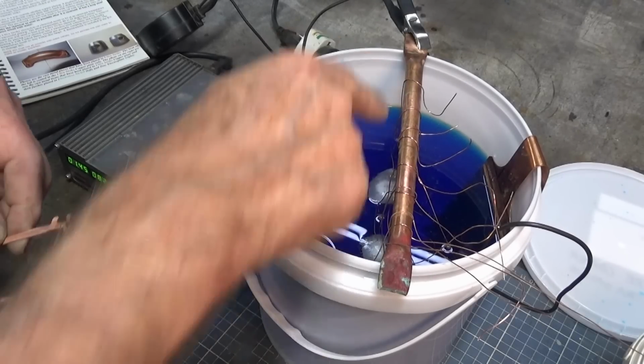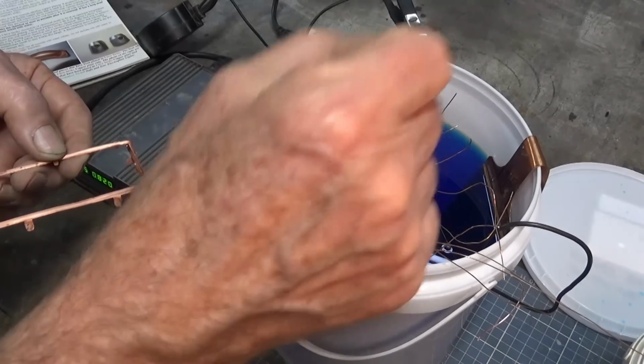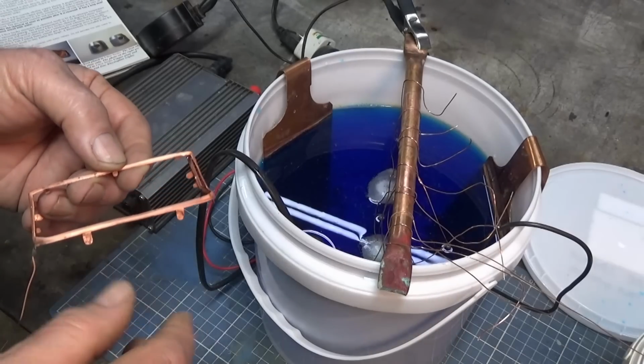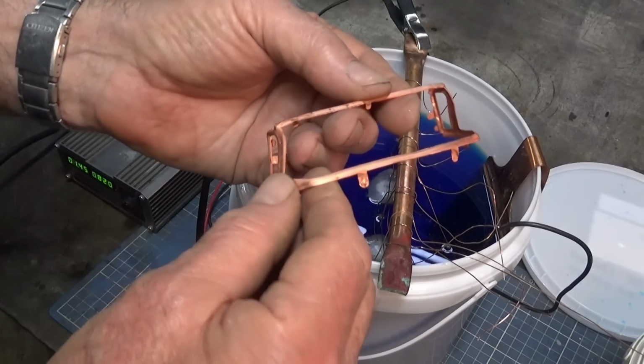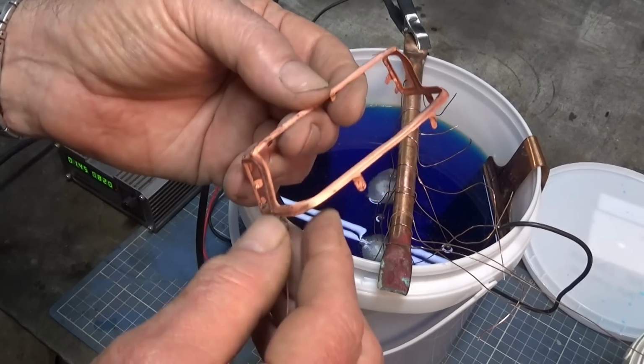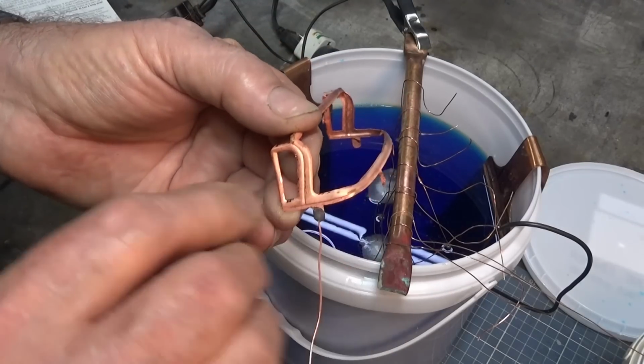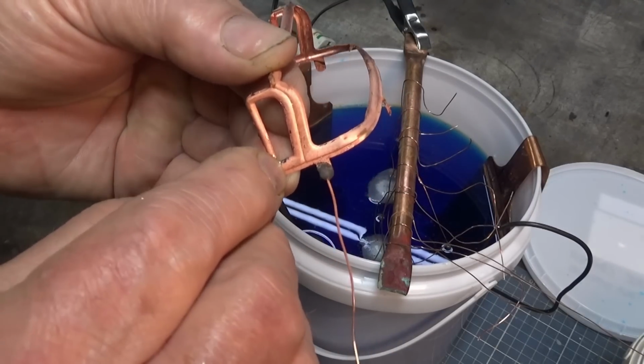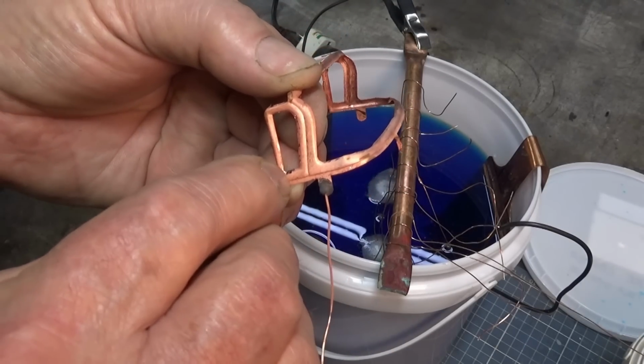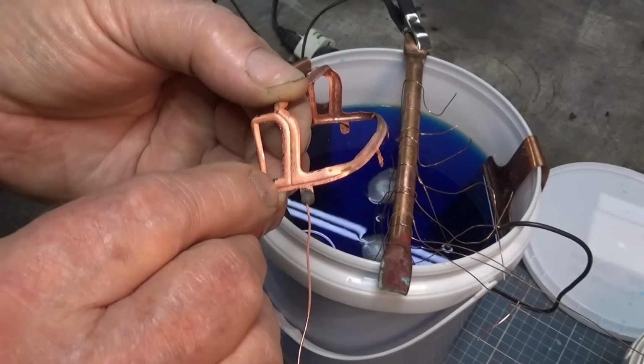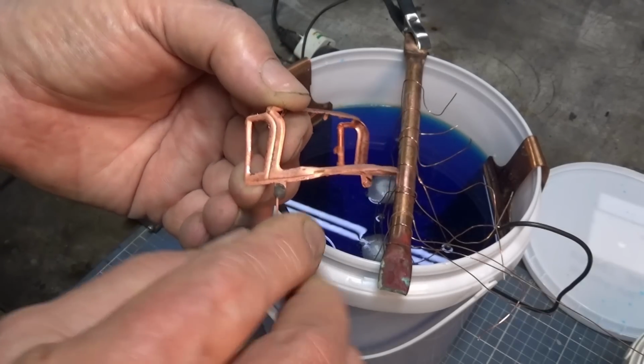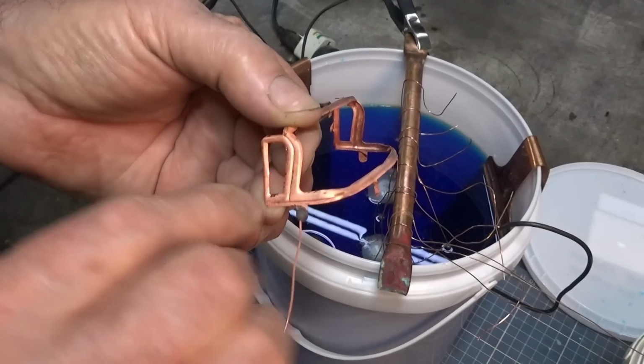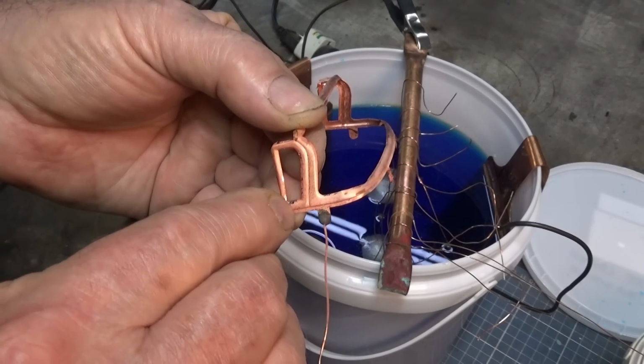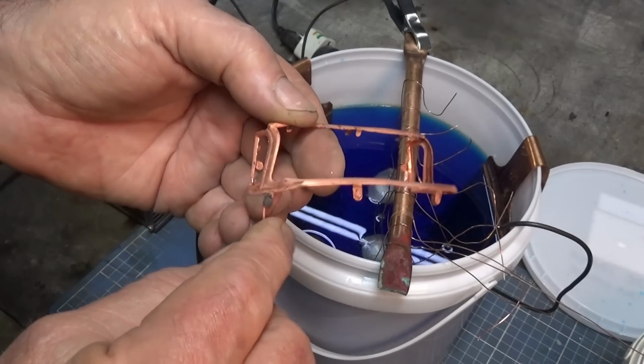Okay, quick update. I'm just doing the last of the parts now, and these are the long, straight, skinny trims that were on that blue Fairlane. And here's one of the windscreen frames that's been done. Now I'm starting to have second thoughts about this. If you look really carefully, you see there's some little speckles of chrome still there, and the copper just didn't go over that. So if I try to do these in the nickel cobalt, it may leave little breaks in the finish, and that may cause corrosion later on.